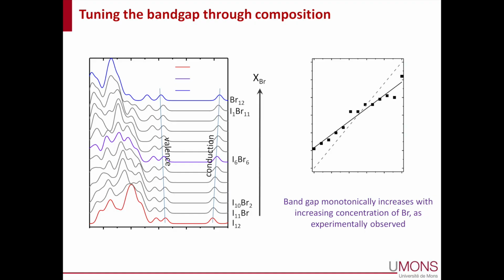So this is a simulation done by Valentin here in the audience, looking at small models for those mixed halide systems, using periodic boundary conditions, of course. When we systematically tune the composition from pure iodine to pure bromine, you can see, quite surprisingly, there is a continuous evolution of the valence and the conduction band edge, and if you calculate the band gap, it follows rather nicely the experimental result.